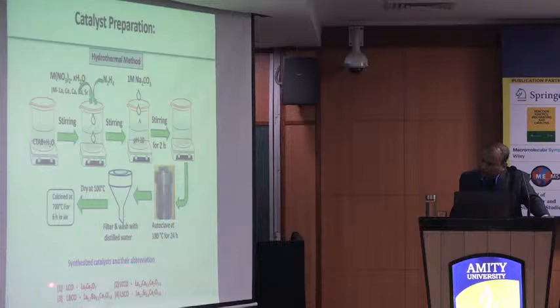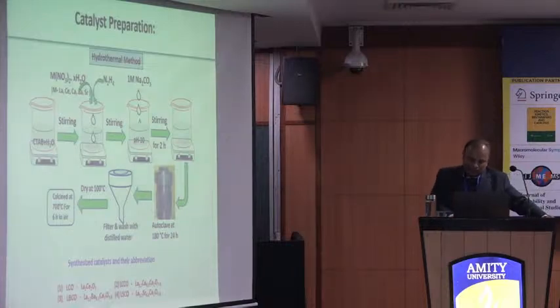And here is the abbreviation: LCO is the lanthanum ceria oxide. LCCO means calcium supported on lanthanum ceria oxide. So we have deposited barium supported lanthanum ceria and also strontium supported lanthanum ceria oxide. But we found that calcium supported lanthanum ceria oxide gives the maximum activity for this methane to ethylene conversion.